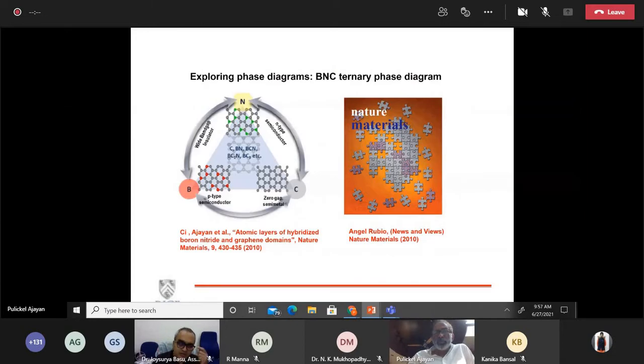We can also go to the ternary phase diagrams in some of these materials, which have many phases that are isostructural. For example, the boron-nitrogen-carbon system is very interesting. Boron nitride is an insulator electrically, and carbon is a metal. And there are many other phases that are semiconducting, like BNCs or BC3. But most of the time when you're trying to grow these kinds of materials, what you end up with is this segregated domain structure that you're seeing in this image.